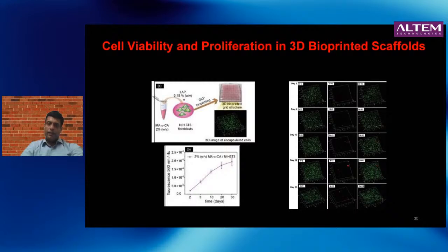And you can see here that from day 2 to 5, all the way up to 30 days, the number of cells is growing. And you can see the images here. These are showing cells that are completely populating the scaffold and demonstrating that this is a great matrix for the cells to grow.